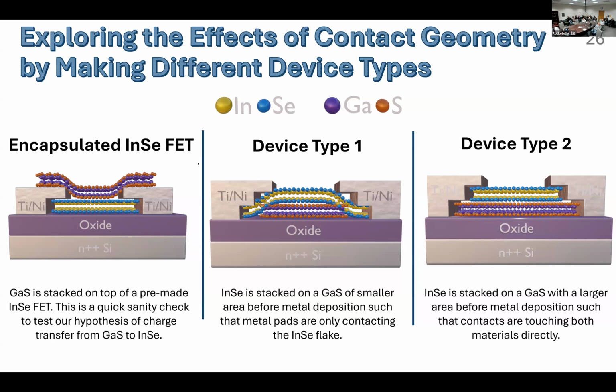Then I will go on to look at what happens if I put the gallium sulfide underneath, as we want to use this as either a dielectric or a substrate material. So it is important to look at how the device would behave if it was placed underneath the indium selenide. However, I will explore two different contact geometries, one in which the contacts are only touching the indium selenide, so that would be device type 1, and another contact configuration where the metal is touching both the gallium sulfide and the indium selenide, referred to now as device type 2.